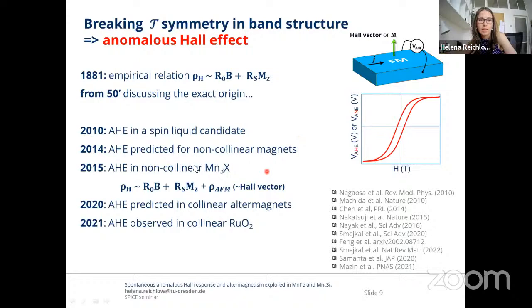In 2015, in milestone experiments, the anomalous Hall effect was confirmed in Mn3Sn and Mn3Ge in the groups of Claudia Felser and Satoru Nakatsuji. And at that time, it was still believed that collinear magnets are simply not allowed to exhibit any anomalous Hall effect, for the reasons which I discussed before, that they do not allow for time reversal breaking in the band structure. This was, however, revisited in 2020 when the anomalous Hall effect was predicted to be present in the collinear altermagnet, and one year later it was also experimentally reported in ruthenium dioxide.